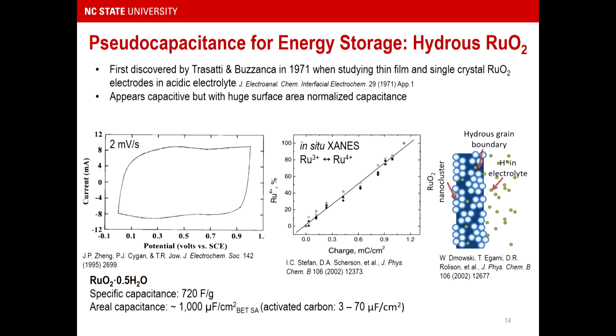In situ X-ray absorption work has shown that this process is linked to changes in the ruthenium oxidation state that are nearly linear with the extent of charge. Although, of course, ruthenium oxide being a metallic conductor, we don't really think about the charges localized just on the ruthenium cation itself. And then this really seminal work by Deborah Rollison on using pair distribution function analysis showed that the structure of this is very, very unique.